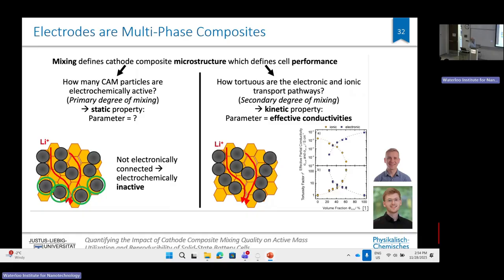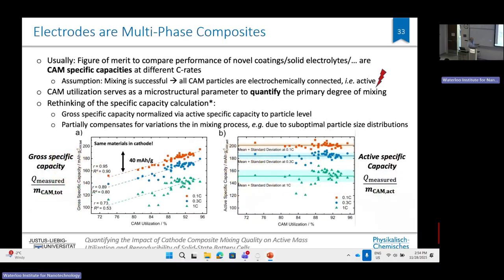This determines, I would say, static connectivity. And then if all are connected, of course you can judge properly the kinetic effect, and that has to be separated. And this is one of the nice things. There was a study last year where 20 labs contributed, and this kind of benchmarking test showed that the 20 labs all got the same materials, had to construct the same cells, and there was a wide variation of results. One of the major factors was that in every lab, the students mostly made their mixtures and cathodes mechanically with a mortar and pestle, and they mixed it a bit somehow, so you have a human factor in that. And if you change that and go to a more professional, machine-made composite, immediately things get better.